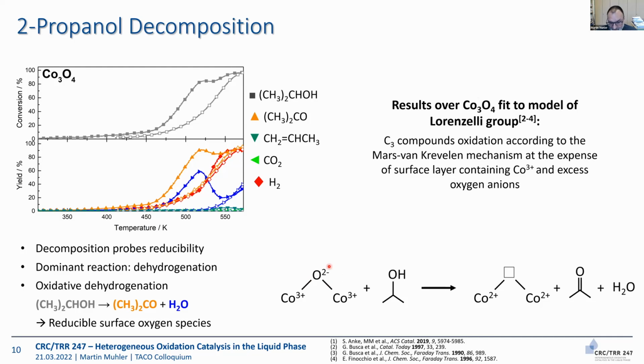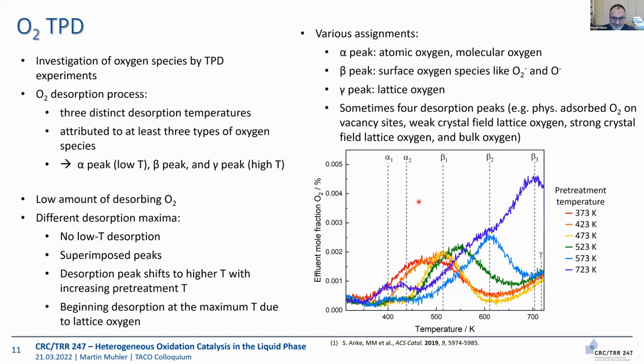And this is obviously what is present on our cobalt oxide catalyst after the calcination in oxygen, the 2 cobalt-3+ ions as electron acceptors and the anionic oxygen here that acts as proton acceptor. And there's also some nice literature from the old days from Guido Busca's group, who has already set up such a very plausible model.